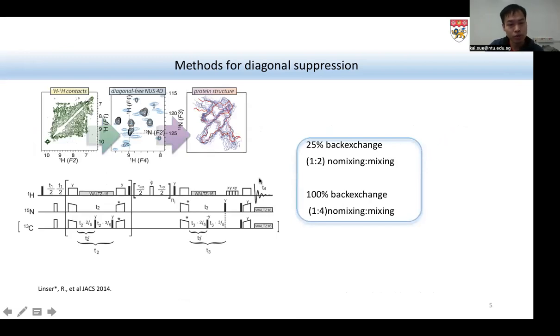And based on proton detection, single-quantum recoupling schemes like RFDR are commonly used. And Professor Linser's group proposed a scheme in 2014 to suppress the strong autocorrelation peaks in 4D spectra, and they demonstrated it on the SH3 protein sample.